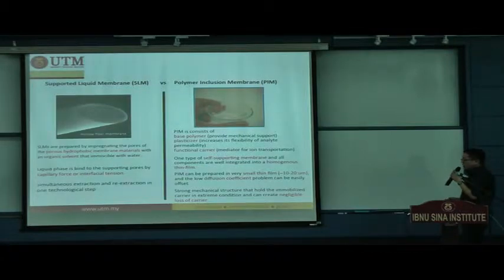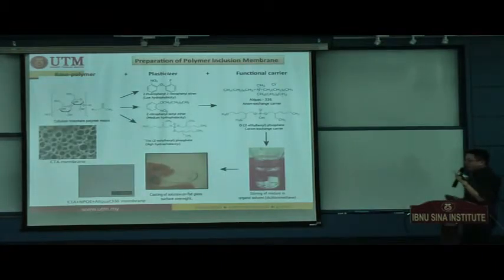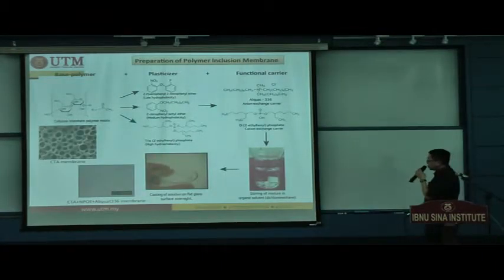The strong mechanical structure holds the immobilized carrier even in extreme conditions and creates negligible loss of carrier. So basically, the carrier that we immobilize in the membrane is always there. It is not going to leak or dissolve into your sample solutions, which makes this membrane possible for a multiple extraction approach. So this is basically how we prepare the polymer inclusion membrane.